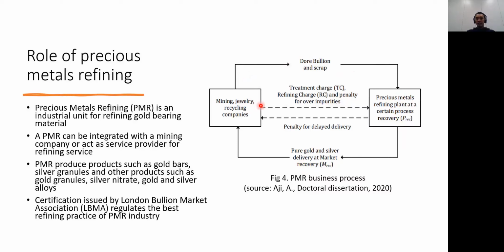And then this is the cash flow. So the mining companies will pay for TC and RC, which is the treatment charge and refining charge. And also the precious metal refinery can pay a penalty if they fail to refine the material at an agreed recovery and time. So in this sense, even though in this metallurgical process we are dealing with high valued materials such as gold, silver, and even PGMs, platinum, palladium, and so on, we cannot really take this process lightly, because the material can be owned by other companies, and we in the precious metal refining can only receive TCRC as our income, so we need to do this process efficiently.